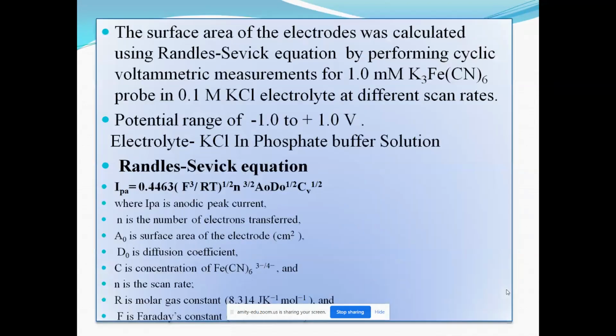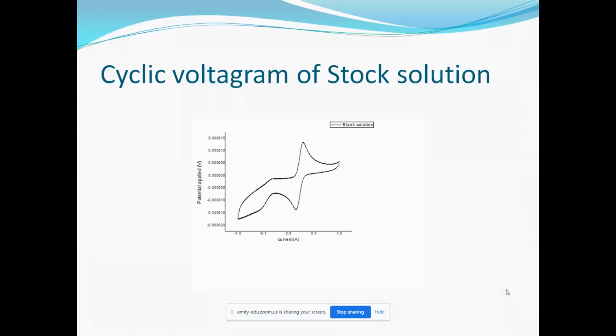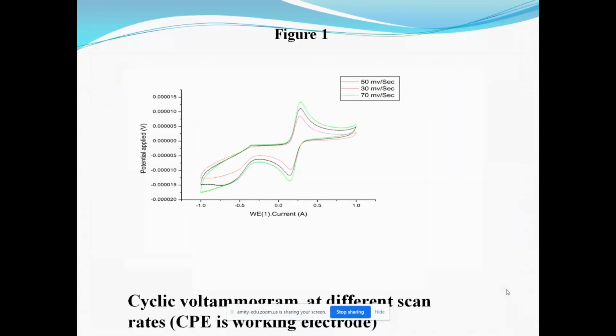For the electrochemical study, I have used a carbon paste electrode as a working electrode and a modified carbon paste electrode, which was modified with the sample, as a working electrode. Ag/AgCl is the reference electrode, and platinum wire is the counter electrode. This is the cyclic voltammogram for the stock solution, for the determination of the surface area of the electrode. These are the cyclic voltammograms of my synthesized compound at different scan rates, with the carbon paste electrode as the working electrode.